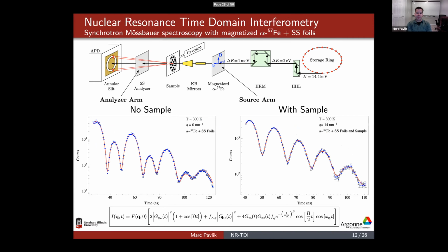So what happens when I put in the sample? Notice that now we add the KWW equation into the sample. This is both at room temperature. This one has the more forward direction. For this one, we choose the peak scattering intensity, which is 14 inverse nanometers. You can see this high-low beat pattern is washed away when the sample is in there. So what is happening is this third term, this cross term here, is being destroyed. And what can destroy that?